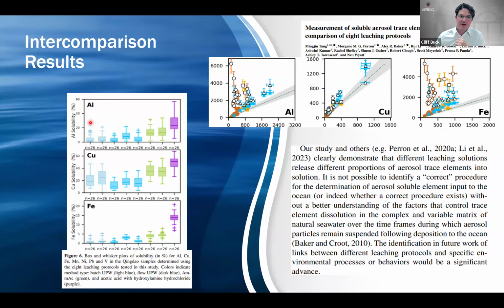And then on the right here towards the top, these are comparing results from just flow-through ultrapure water leaches, okay? Ostensibly we should be getting the same answer, except one of these groups was not using a backing filter behind their aerosol filter. So when the water was going through the aerosol particles, potentially those particles were washing through because they were smaller than the porosity of the filter, right? The other groups had 0.2 micron backing filters to retain those particles. As a result, the group without the backing filter had apparently much higher solubility, or a larger soluble fraction, because these very small particles were washing through.